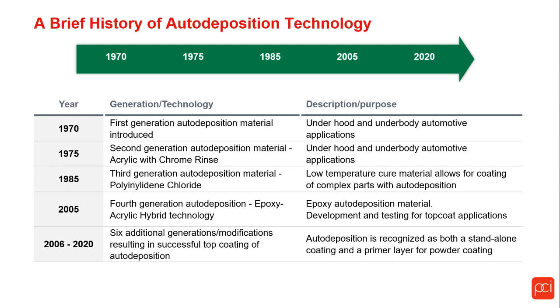Shortly after this technology came out, it was looked at as a primer layer for a top coat application. Between 2006 and current, 6 other generations have been introduced, and we have been able to successfully top coat the product with powder coat, which we'll discuss in a few slides. But this material's been around for about 50 years, and it is recognized as both a standalone coating and also as a primer layer for powder coating.